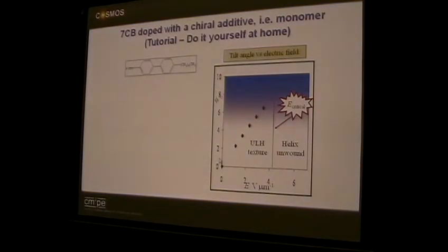So in here, you get a rotation of the optical axis with a field. And note that they're very low fields, 2 volts per micron, 3 volts per micron, very, very low. In many devices, you work up to 10 volts per micron. Okay. So you have a very low field, you have a linear effect. In 7CB, why you wouldn't use it is you get a critical unwinding field at about 4.2 volts per micron. So beyond that, it unwinds the helix.